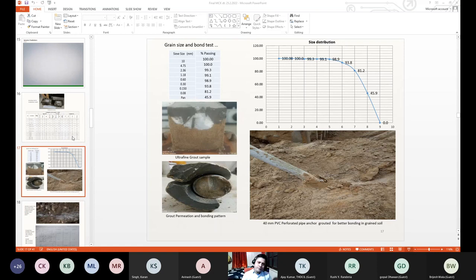Okay. Please continue. The grouting was done to prevent the free-flowing water with this 100 kg cement, WC 0.8 and admixture 1.5, and no other chemical was used. I just wanted to see whether the cement simply stops the water or not. You are watching the packer. It is a hydraulic packer which we kept 2.5 hours in the hole, and after 2.5 hours it was difficult to take back because the system was not able to take it back, as sometimes the grout pressure comes back, and it may be dangerous.